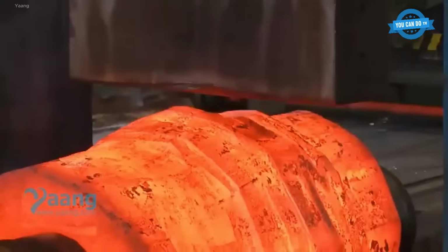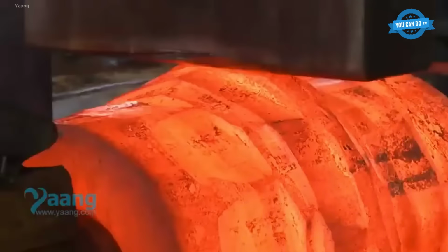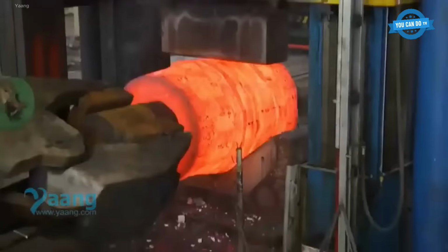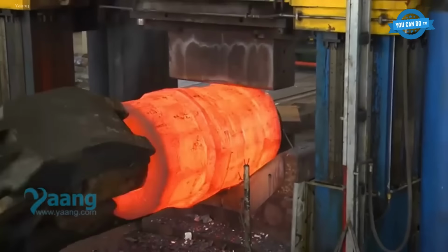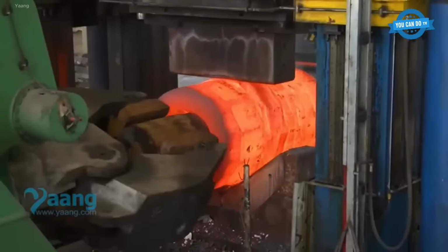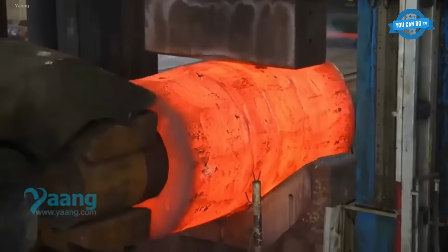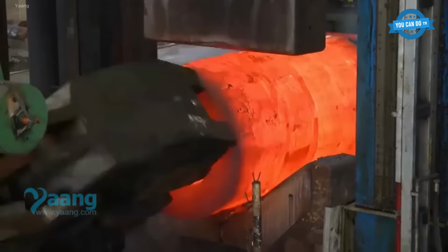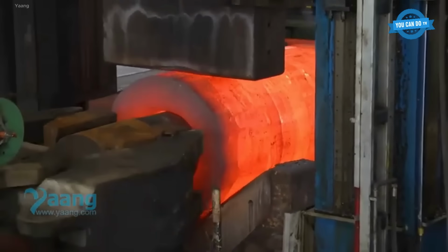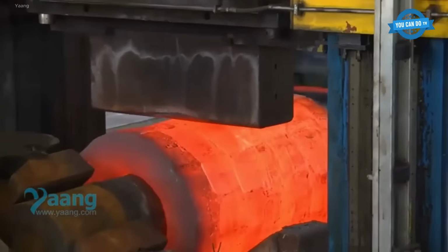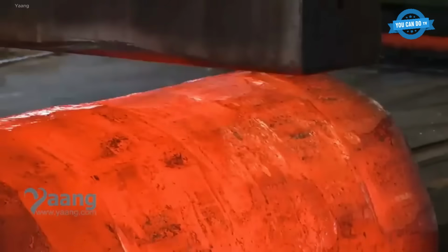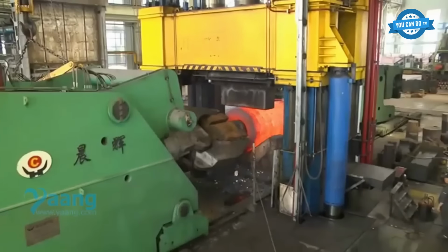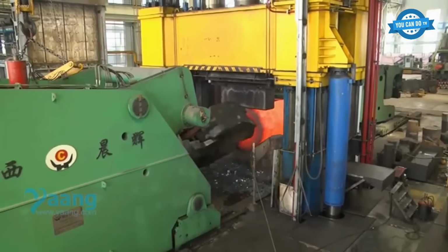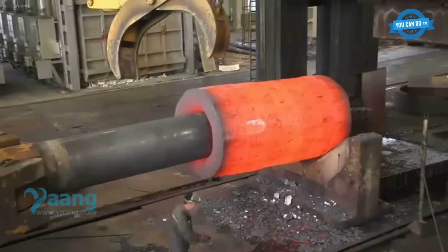Post-treatment, forgings are visually inspected for dimensional accuracy and surface integrity. Precision machining removes excess material and sharp edges, improving the final geometry. Non-destructive testing, UT and MT, is carried out to detect internal flaws. Hardness and dimensional inspections validate mechanical performance. Quenching and tempering follow if higher strength and toughness are required. Another round of UT, hardness, and grain size testing ensures compliance.